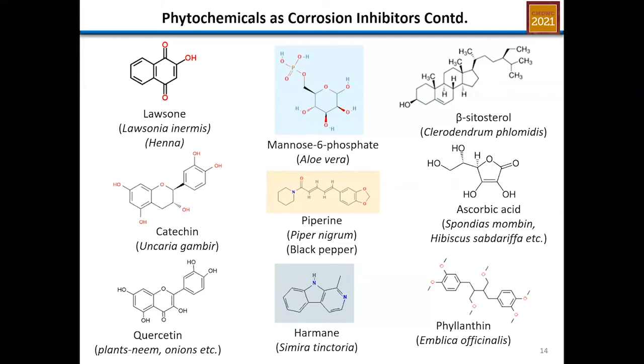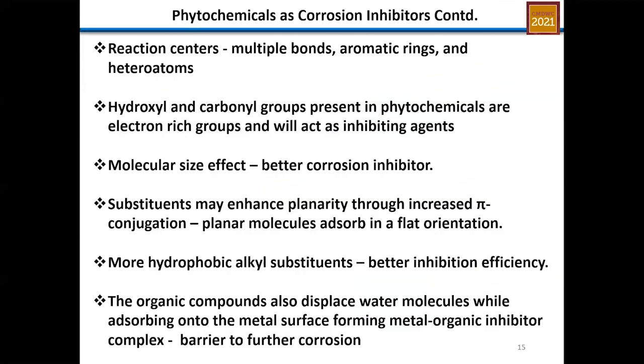Now, the main aim of utilizing these phytochemicals is because of the heteroatoms that they have. If you take a look at the structures, you find out that they have carbonyl groups, hydroxyl groups, phosphate groups, large aromatic rings, nitrogen groups, etc. So the reaction centers here are multiple bonds, aromatic rings, and heteroatoms. The hydroxyl and the carbonyl groups present in the phytochemicals are electron-rich groups, which will act as the inhibiting agents.